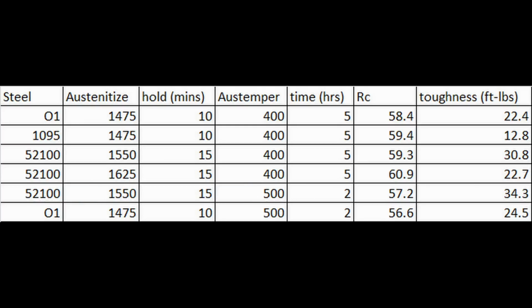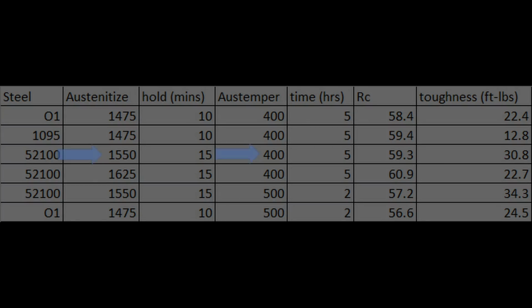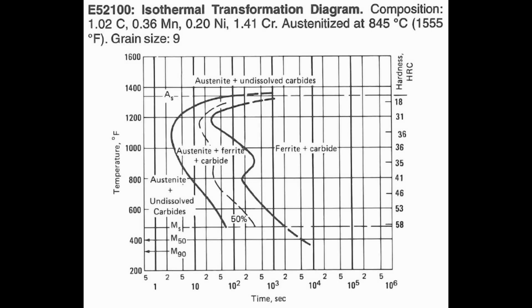That was the same treatment we were discussing on the TTT diagram, where 500 degrees Fahrenheit was about the minimum temperature you could use before martensite would start to form. And I held that for 2 hours. Another experiment I tried was 1550 austenitized with a 400 degree Austemper. Looking at the TTT diagram, you can see that this should have about 50% martensite.